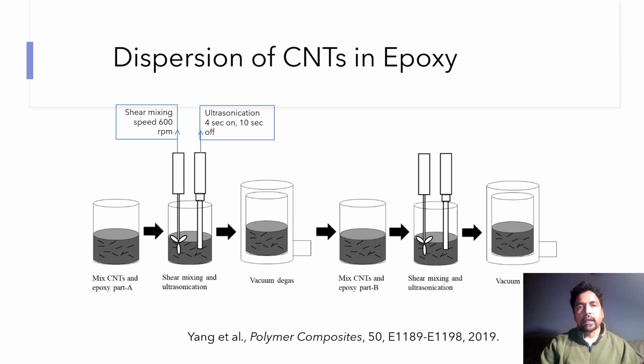As you see in this picture, we have a dispersion of carbon nanotubes in the epoxy matrix. This is accomplished by employing a combination of shear mixing and ultrasonication. First, we mix the required amount of carbon nanotubes in part A, which is the resin part of the epoxy, and then we use a combination of shear mixing and ultrasonication to disperse these carbon nanotubes both microscopically as well as macroscopically. Ultrasonication disperses the carbon nanotubes at nanoscale, and shear mixing disperses them macroscopically, which is very important to avoid segregation and clustering of these carbon nanotubes.